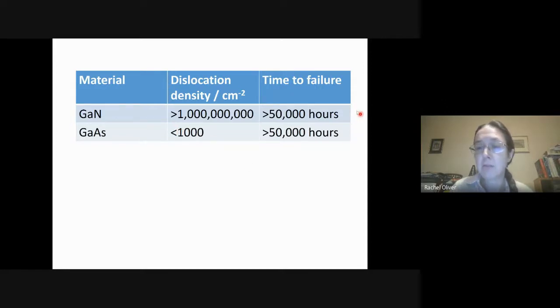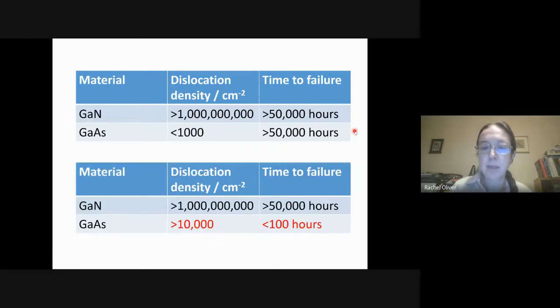But actually both types of device work really well. They're both long-lived, with lifetimes in excess of 50,000 hours. But if we were to take our gallium arsenide and increase the density of defects by about a factor of 10, the lifetime of that gallium arsenide device would drop from maybe 100,000 hours down to less than 100 hours. And in fact, the gallium arsenide device might not really work at all. Gallium arsenide devices with a high density of defects very quickly become hot, and then the heat causes them to fail. And in the worst case, you would pretty much turn them on, wait for a second, and the whole device would go phut, and that would be it.